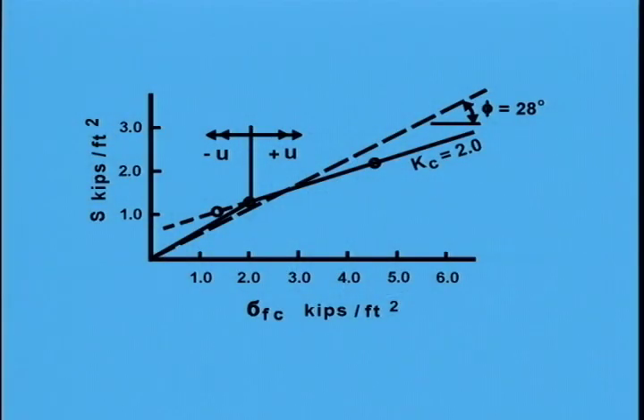The design curve for determining the shear strength values to use in the after drawdown stability analysis consists of 2 straight lines. For higher sigma Fc values, where positive pore pressures occur at failure, the actual laboratory test results are used, as indicated by the line labeled K sub C equals 2. Where tensile pore water pressure occurs at failure, the strength is reduced to that consistent with 0 pore water pressure. It does not seem reasonable to rely on soil strength developed due to tensile pore water pressure.